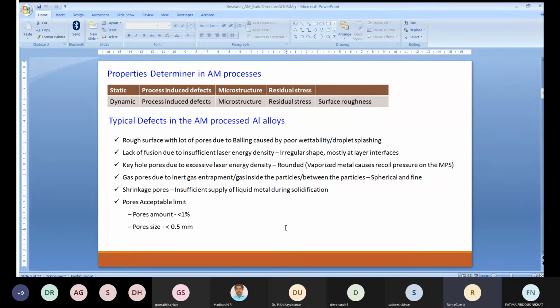This gas can come from gas trapped in between powder particles or gas inside the powder itself. If you take a single particle, there is also a possibility that gas can be inside. You also use inert gas in the build chamber, which may also get entrapped, causing the gas porosity. How to identify? Its shape should be spherical, and it is fine and scattered.